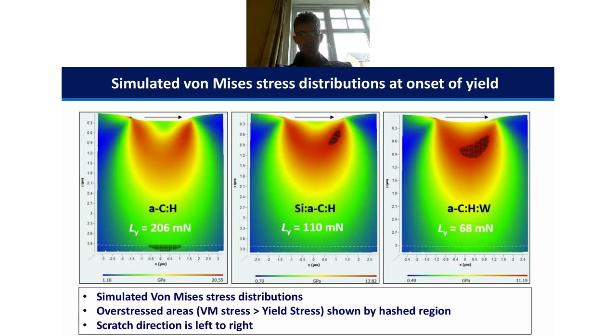The red areas are the highest stresses, the blue areas are the lowest stresses, as you can see if you can just make out the key there. And these hashed regions are the regions at which the stress developing in that contact is higher than the yield stress of that particular part of the system. And straight away we can see some clear differences in these systems. We can see for this one it's very overloaded within the coating. Conversely, when this harder system yields, it's actually within the steel substrate and not within the coating. So this has differences in terms of their wear resistance in nanofretting tests and things like that.